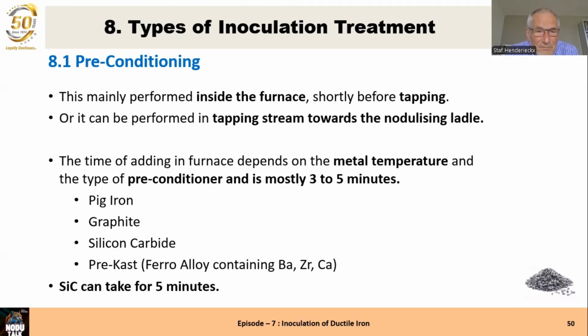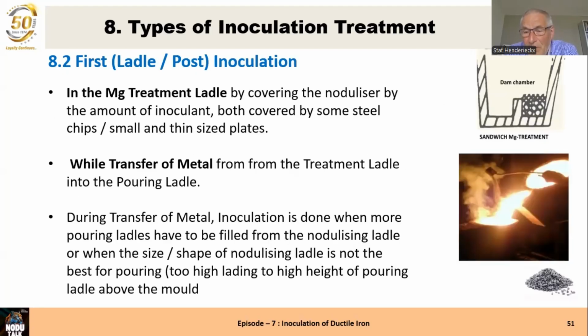Next slide. In the first ladle, we have seen that you can put it together with the nodulizer, and both covered with the steel chips and small thin sized, as you see, the sandwich method in the figure at the right. You can do it during the tapping itself. You see it in, but I don't like that much, because due to the high temperature and the heat movement, you will lose some of them. So pay attention for that.